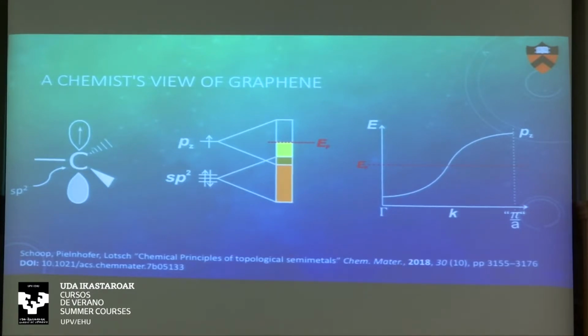So if you look at graphene, we look at one carbon atom, and we say, okay, it's sp2 hybridized, forms 3 bonds, and then it has a pz orbital, and there's 1 electron left in the pz orbital. So if we draw a band structure, we draw the sp2 manifold, and we say this is completely filled because it's all bonded and saturated. Then we have a pz orbital, which has 1 spin in it. And we also know it's not really just a molecule, it's an extended network, so we have to extend it to bands. Then we have a fully filled sp2 band and a half-filled pz band.